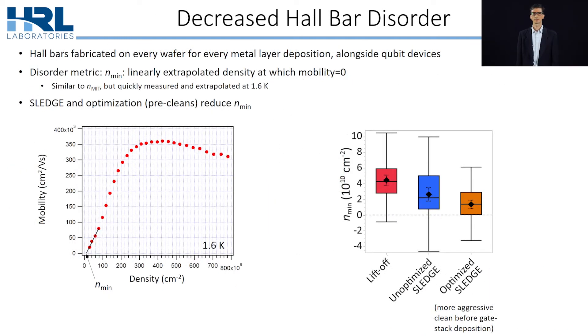Next, I want to show disorder metrics from Hall bar measurements. In our fabrication, at every metal deposition step of a qubit device, we also make a Hall bar. Our measurement disorder metric is the linearly extrapolated density at which mobility goes to zero, and we call this n_min, though there are a few other names for this. It is very similar to a percolation density or metal-insulator transition density. We found that the advantage of this linear fit n_min is that it is quickly measured and repeatable. From the n_min statistics at the right, SLEDGE has a lower n_min than the traditional liftoff process. Further, the optimized pre-clean SLEDGE devices have lower n_min than unoptimized SLEDGE devices. These reductions in disorder help with in-device tune-up, calibration, and software automation of these steps, which is something HRL is pursuing and my colleagues will be detailing in other talks.